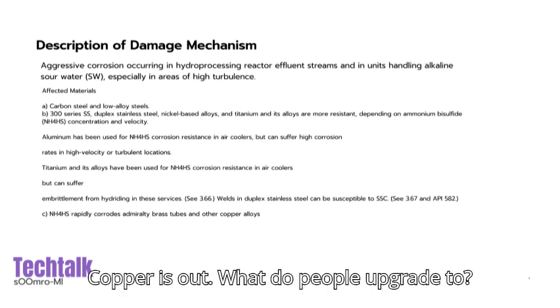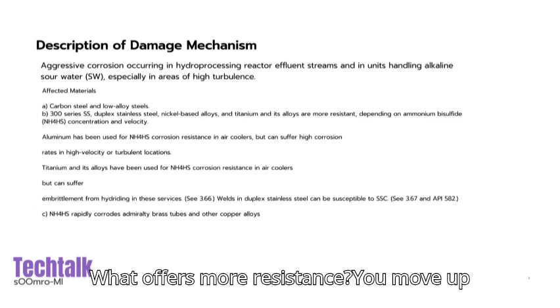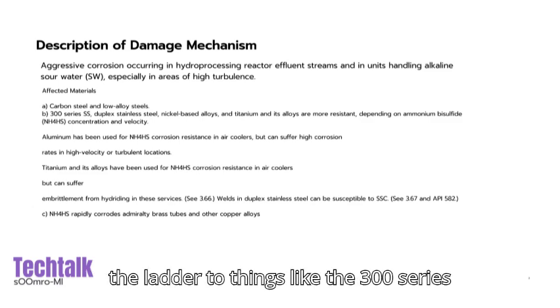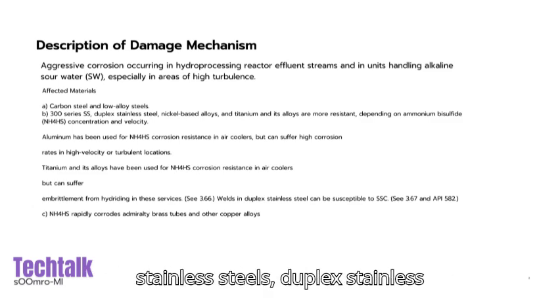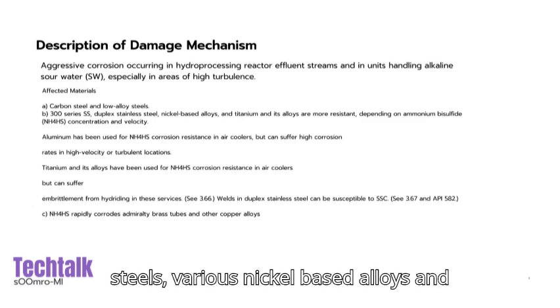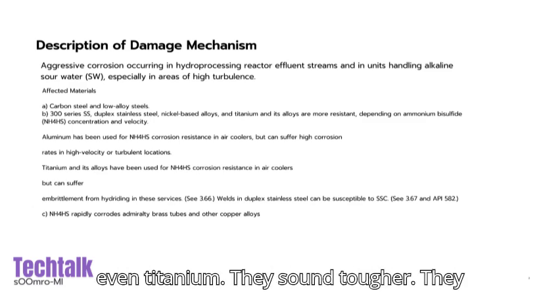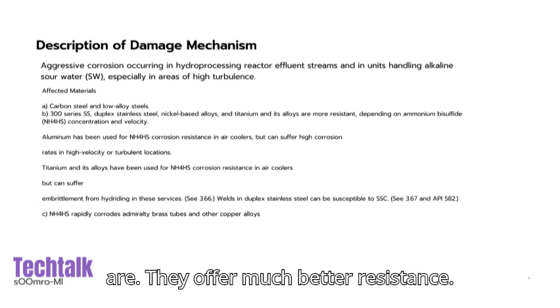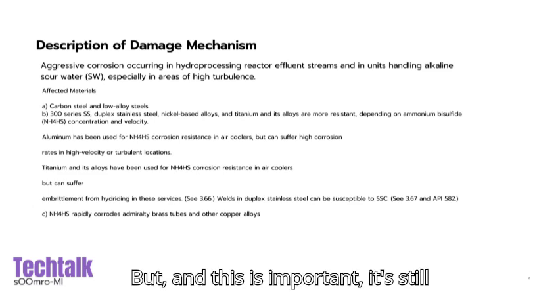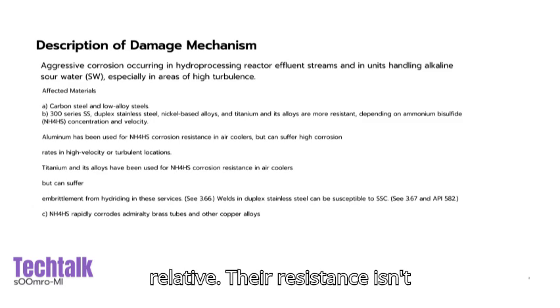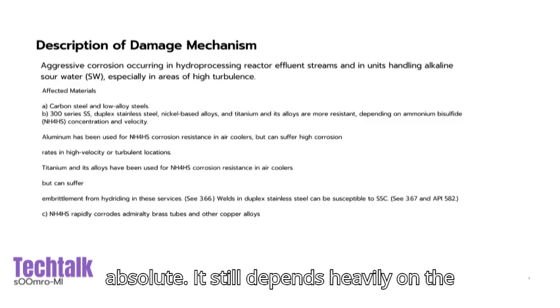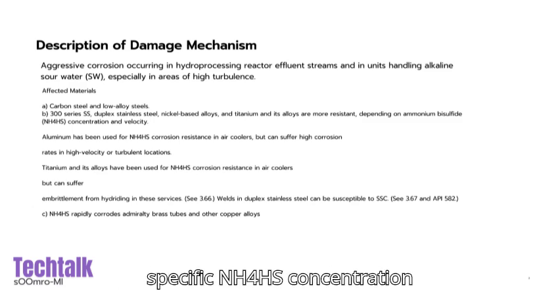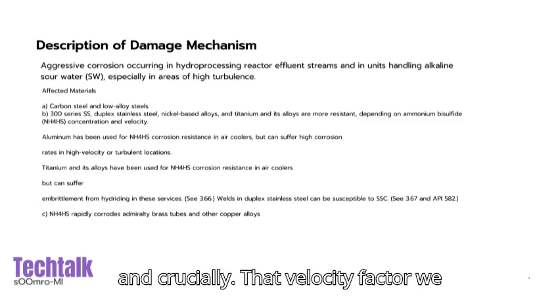Yeah. What do people upgrade to? What offers more resistance? You move up the ladder to things like the 300 series stainless steels, duplex stainless steels, various nickel-based alloys, and even titanium. They sound tougher. They offer much better resistance. But, and this is important, it's still relative. Their resistance isn't absolute. It still depends heavily on the specific NH4HS concentration, and crucially, that velocity factor we talked about.